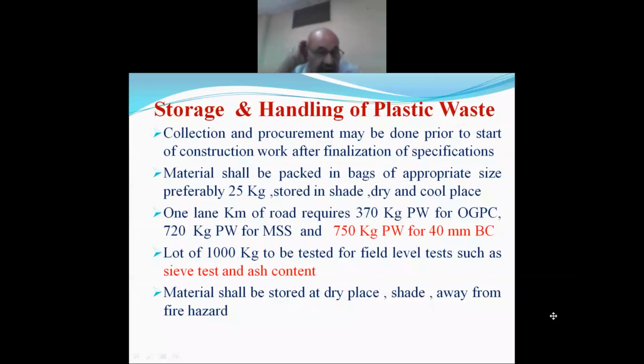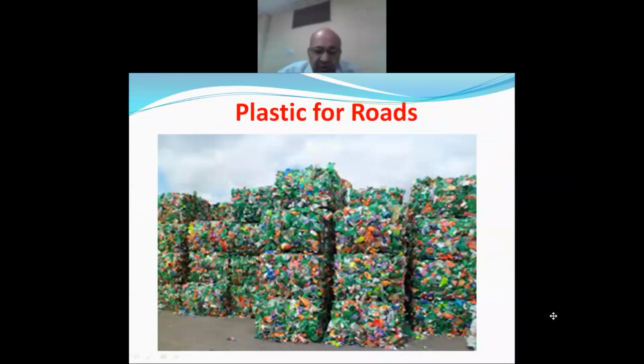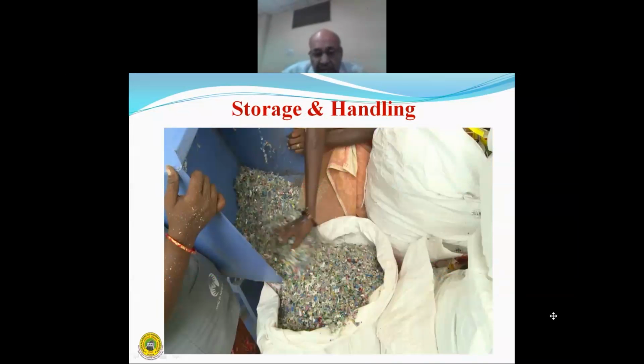Now I will give you some tips about supervision of the construction and quality control. First of all, one of the important aspects is storage of the plastic because it is a flammable material. It can catch fire, which may become a serious problem. For storage and handling of plastic, collection and procurement may be done prior to start of construction work after finalization of the specification. Material shall be packed in bags of appropriate size. It will not be stored in the open, preferably 25 kg bags, and it should be stored in a shaded, dry and cool place.